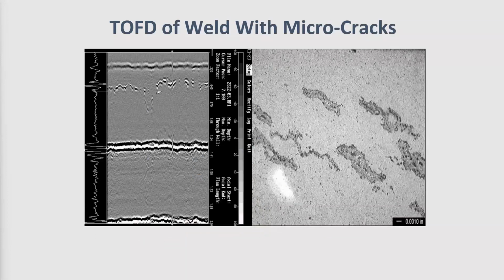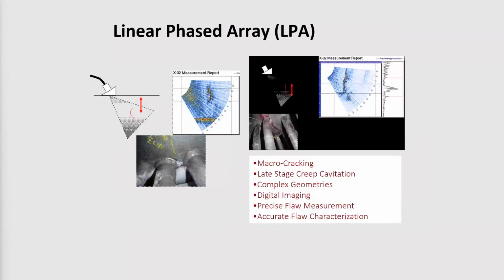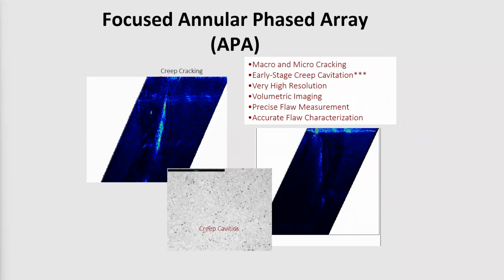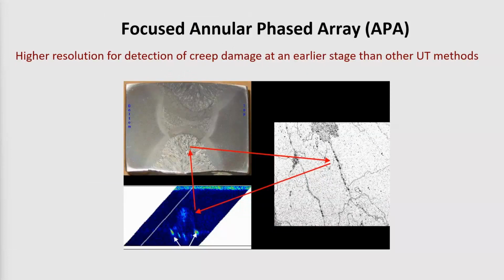The time of flight diffraction method has a particular level of damage that it can detect. Go to linear phased array. It also has a particular level of damage that, based on that technique, it's able to identify. And then what's called focused annular phased array, or other techniques now, these matrix type techniques, are able to focus the sound energy in a way that can give a higher level of resolution to what can be seen. So these would probably represent the best level of resolution that can be achieved with ultrasonics. And in those cases, you can find the damage at a slightly earlier stage.